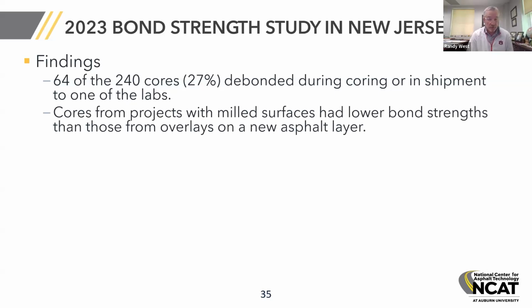Cores from the projects with milled surfaces on the New Jersey project had lower bond strengths than from the overlays on a new asphalt layer. My hypothesis here is that since they were milling, cleaning, tacking, and paving all at night in one, probably less than 8-hour shift, I don't think the surfaces were getting cleaned well in some cases. We didn't measure cleanliness. We weren't there to really observe it. We saw just some pictures from when they were doing the coring, but that's my hypothesis. I don't think they were getting some of the dust, the debris from milling out of the milled surface with the textures that they have.